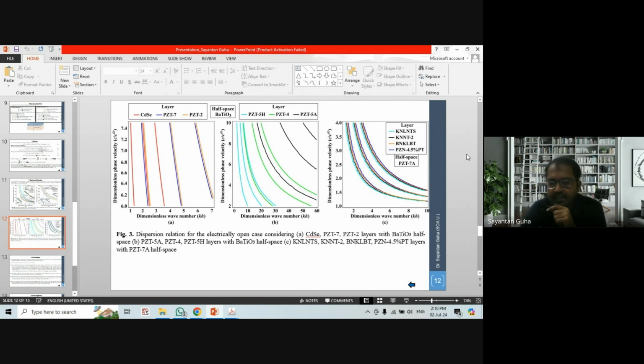Lastly, for the PZT7A half space, I've considered these 4 different types of layers, and it can be seen that the combination KNLNTS along with PZT7A gives us the least phase velocity, followed by KNNT2, BNKLBT, and PZN 4.5% PT, which gives us the highest phase velocity. So over here, we can conclude that if the SAW device is composed of KNLNTS with PZT7A, then the phase velocity is the least, and that device is going to give us the most enhanced performance compared to all other structures.